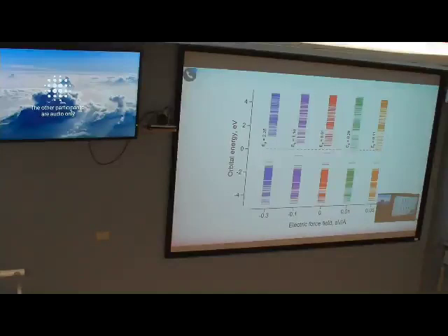So for negative field, HOMO goes lower, and for positive field, HOMO goes higher and intersects the Fermi energy. So for positive values of electric field, the gap comes to zero, and further HOMO and LUMO swap their order.